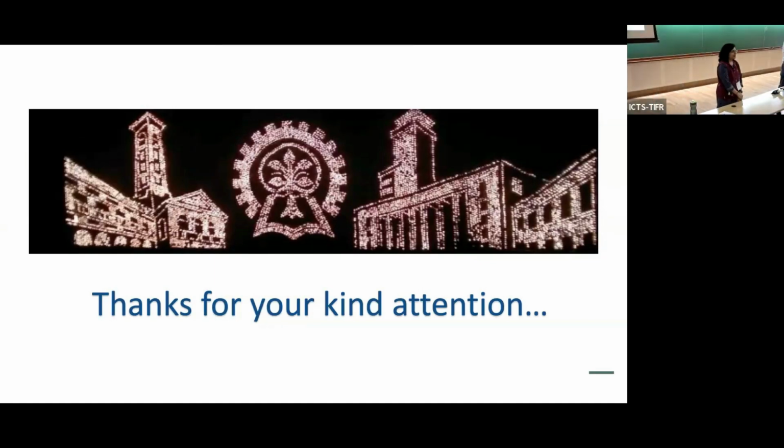So it is actually not about acceptability. What I showed you here is when you try to grow this 2D material on top of sapphire. Once you see that there is this kind of Raman shift, it shows that the optical properties are significantly influenced. But you can always have the option of transferring this to a new substrate. It becomes important when you're trying to grow these heterostructures directly. For example, if I'm trying to grow WSe2 directly on top of hBN, and if these kinds of lattice strain factors are affecting it, then it is going to be important to look at.